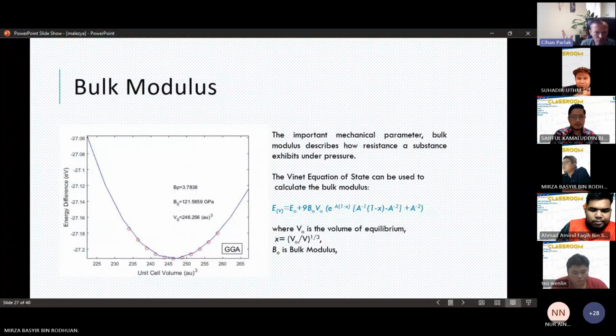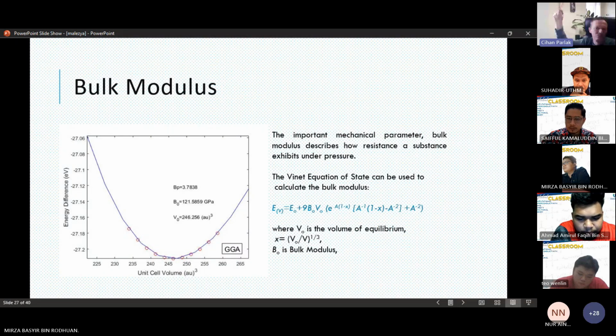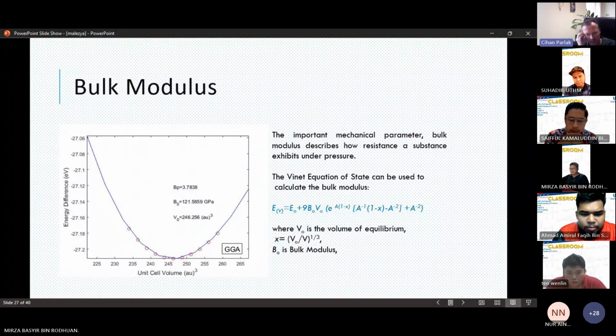After the convergence test and geometry optimization, we can easily get bulk modulus values. It is an important mechanical parameter that describes the substance's resistance to pressure, and you calculate it from the optimized A and C values. You change the volume slightly and again calculate the ground state total energy. Every time you put these values on a graph and fit these energy-volume values to an equation of state, such as the Murnaghan equation of state or the Vinet equation of state, and you can easily calculate the bulk modulus. The bulk modulus of calcium diboride is 121.5 gigapascal for GGA exchange correlation, as you see. Next slide, please.